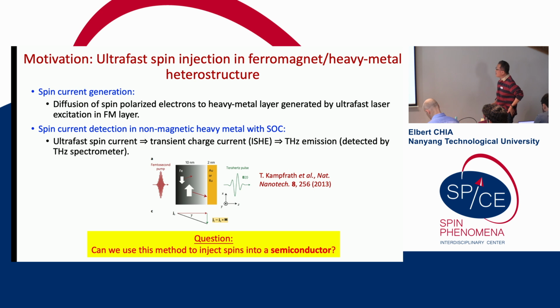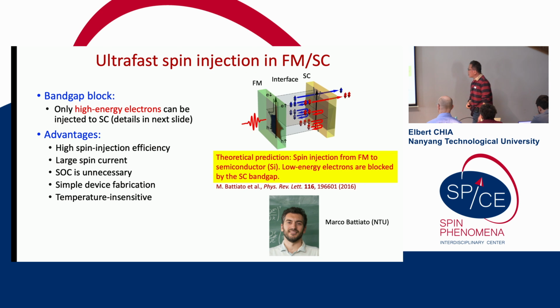So the motivation of our work is, once again, Tobias' work in 2013. Many speakers have already talked about this, so I'm not going to belabor the point. But we ask ourselves this question: what if we replace this heavy metal by a semiconductor? What will happen? And so when Marco was a postdoc, he suggested this scheme that even if you have a semiconductor, the spins are able to be injected into the semiconductor only if the carriers have very high energy. The advantages of this is that you get very high efficiency, you get a very large spin current, you do not need large spin orbit coupling. The device fabrication is simple, and this is a temperature insensitive process.